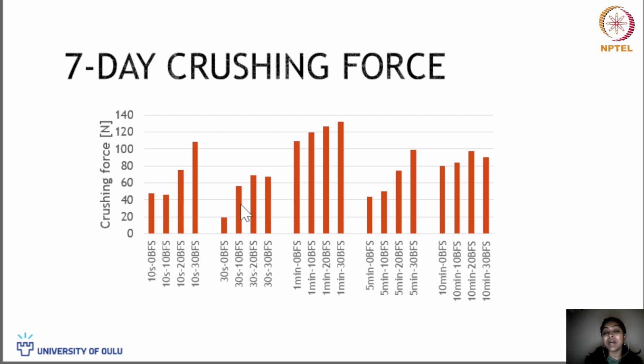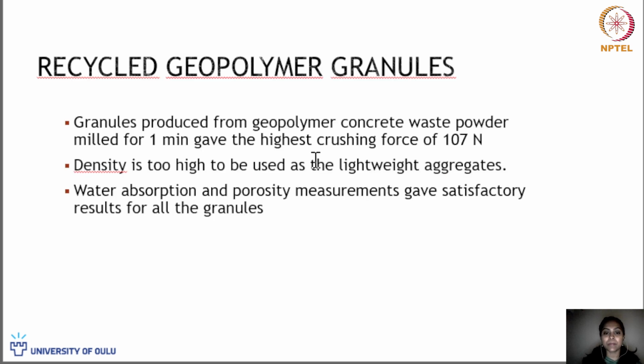This is because of the particle packing effect. So at this 1 minute ground sample, the particle packing or the particle size distribution was perfect to produce a better, compact packing that gives you the higher crushing force. So recycled geopolymer granules, like I said, gave the best crushing force of 107 Newton at 1 minute. The density seems to be very high to be used as a lightweight aggregate in this case, and the results were satisfactory to be used as a lightweight or a regular weight aggregate concrete for construction.